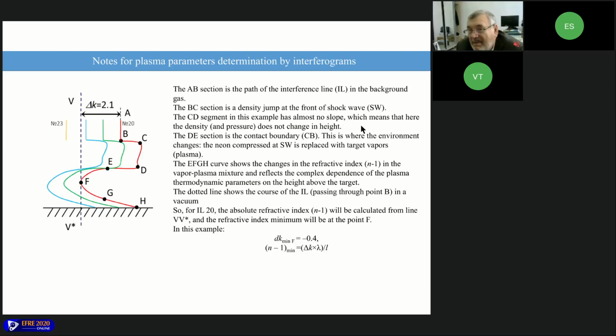If we look at the sections of lines, we see not disturbed background gas in the AB section, the shockwave area at the BC section, and the density jump. We have no significant slope on the CD section, which means that the density does not change in height in the compressed gas. And the other section, DE, is a contact boundary between the phase of vapor plasma and compressed background gas.